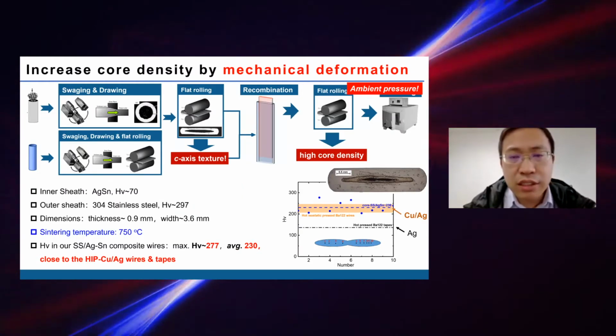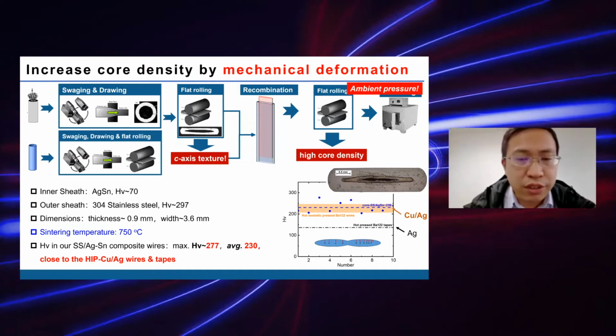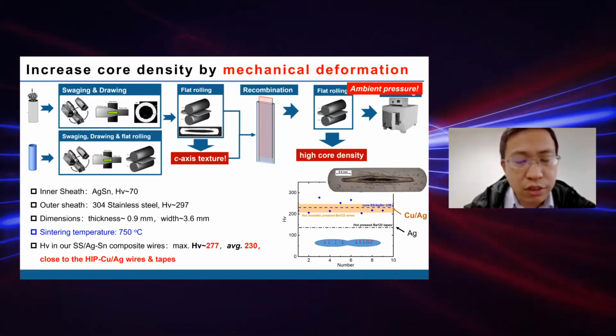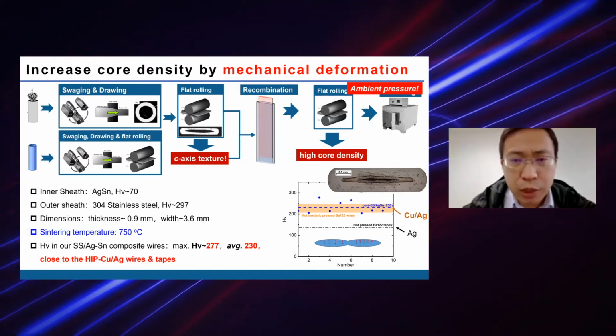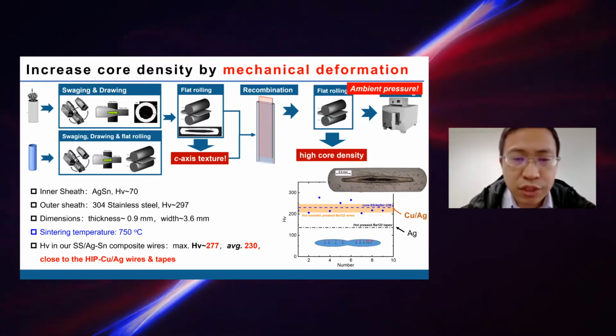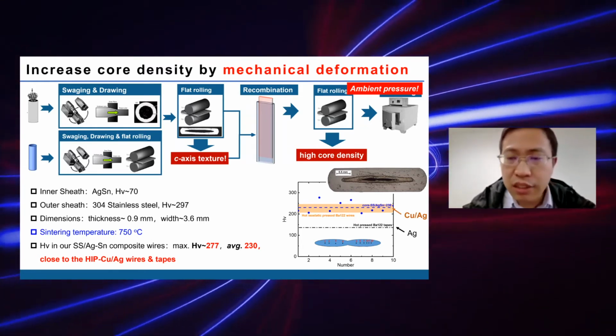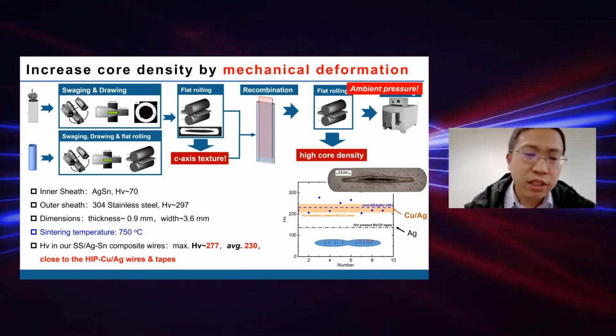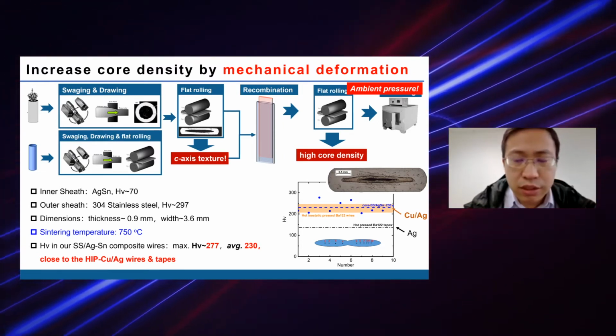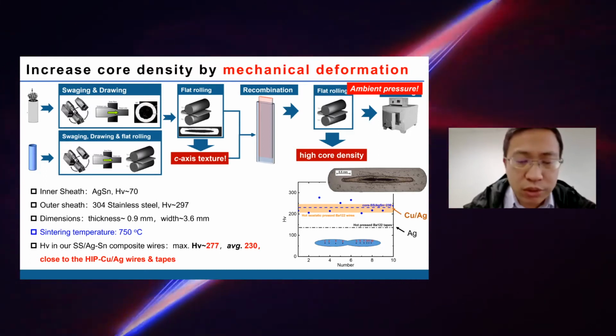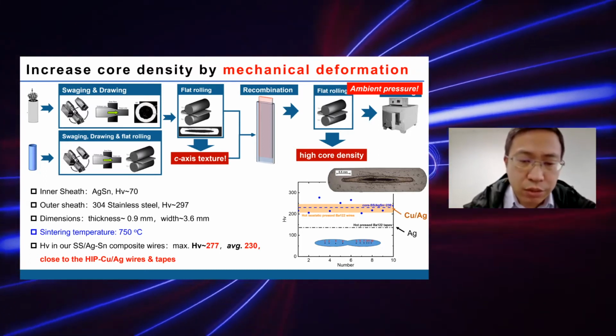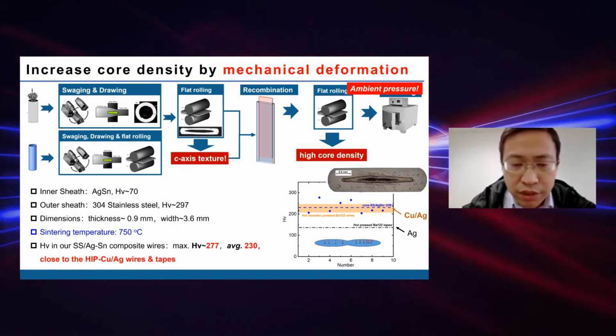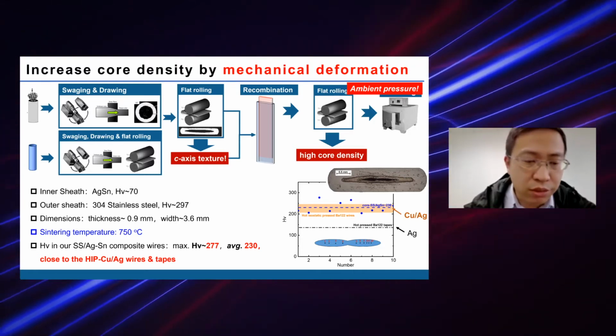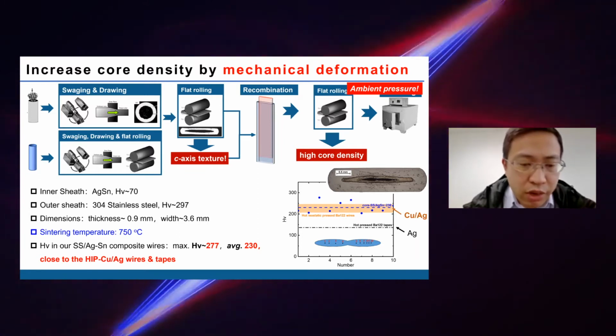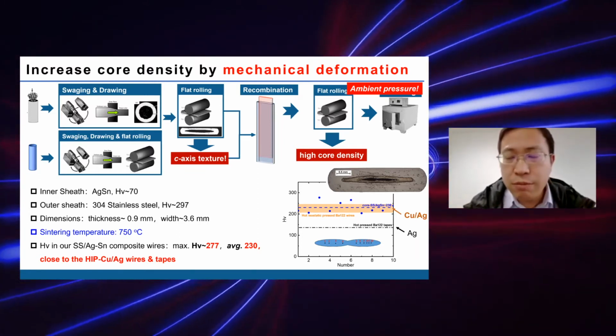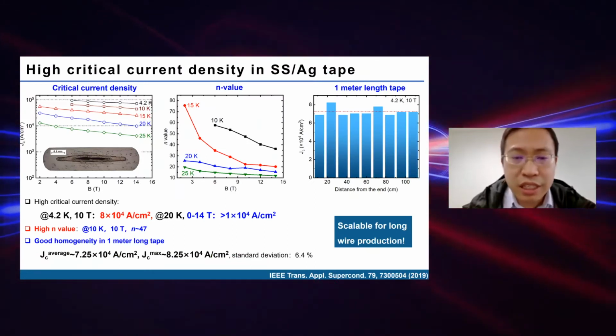The second one is mechanical deformation. And here is an example. We use a stronger outer sheath, stainless steel, and by flat rolling, we can introduce c-axis texture and high core density as well. The Vickers hardness of the surrounding core can be increased to 277, which is very close to the HIP wires and tapes. And we have fabricated a 1 meter long tape.